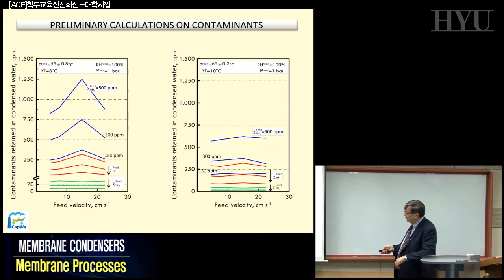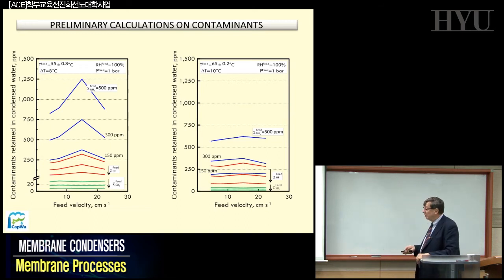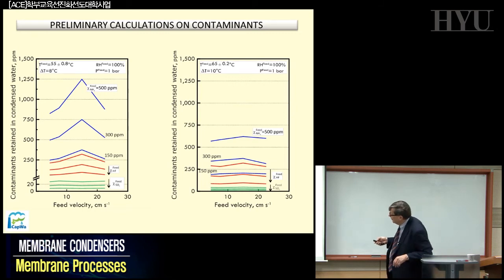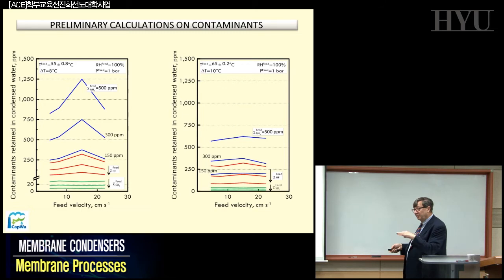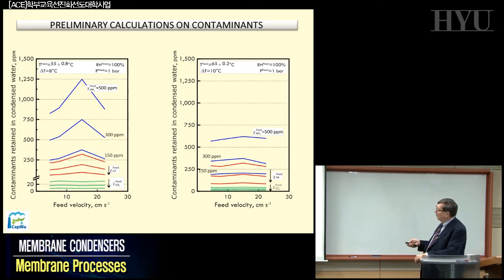With the membrane condenser this can be done by controlling the cross flow, the feed velocity on the membrane surface. Or better than this, by controlling the parameter I was showing before, that means the feed velocity divided by the membrane surface available. You can see here that if you have ammonia or hydrofluoric acid or SO2, etc., present in the stream, by changing the cross flow velocity you can significantly change the concentration. You can go through a maximum, so you can minimize or you can maximize the level of some of the contaminants present. In some cases, you want to eliminate them because they can be dangerous for the final utilization of the liquid. In some other cases, you want to recover as much as possible because you want to reuse them eventually in the process itself. Normal condensers are not doing this. Membrane condensers are doing this.